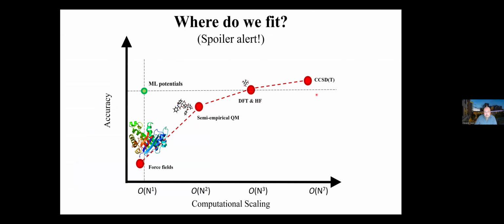And therefore, the promise of these machine learning potentials is that if you train your ML model, for example, on density functional theory data, you can essentially make a method that has favorable scaling. Neural networks are linearly scaling, and you can approach the accuracy of the reference theory, for example, density functional theory. And therefore, you have this 4 or 5 orders of magnitude speed up for those simulations.